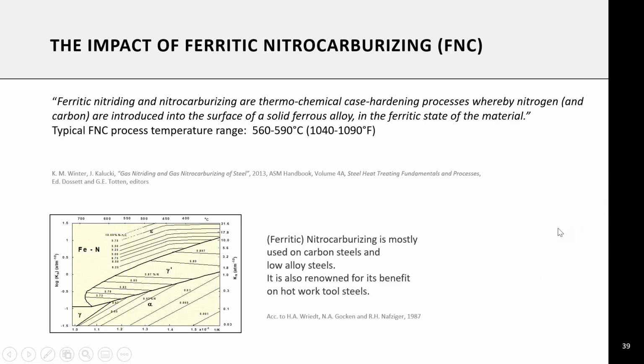Thank you. So how does ferrite nitrocarburizing actually work? In essence, what you see in that small table here, the layer diagram, is that you build on top of, say, carbon steel or cast iron a white layer. White layer is a quasi-ceramic layer which can take up to 10% of nitrogen by volume, the rest could be iron or alloying elements. But the interest is that it has low conductivity, which makes it interesting for corrosion resistance, and it also resists wear because it is extremely hard. Next, please.